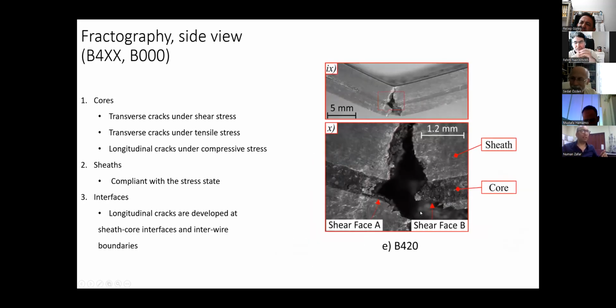And the interwire and the sheath core interfaces, the diffusion bonded interfaces, fail with the longitudinal cracks. Here you can see, again, this can be said that the transition zones, which were loosely bonded iron boride phases, or maybe the presence of ferrite phases at the sheath core interfaces and the interwire boundaries, might have caused them to fail in longitudinal cracks, because shear stresses tend to break them at the weakest area.